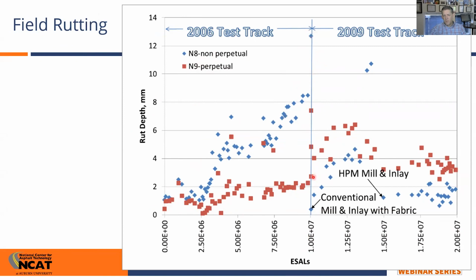We did the conventional mill and inlay to bring it back down. And then in about 3.5 million ESALs, we're approaching a failure point again. This is where we said, well, we've got to do something more aggressive. We did the high polymer mill and inlay, and then it maintained itself in terms of rutting performance through the end of the test cycle.